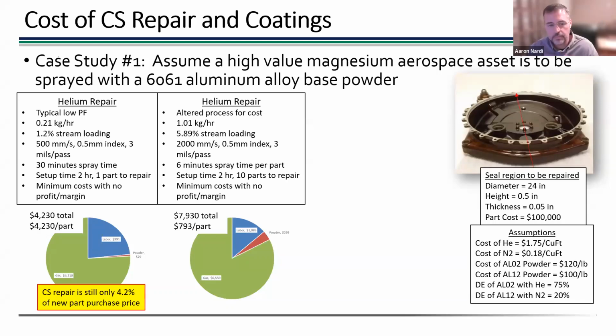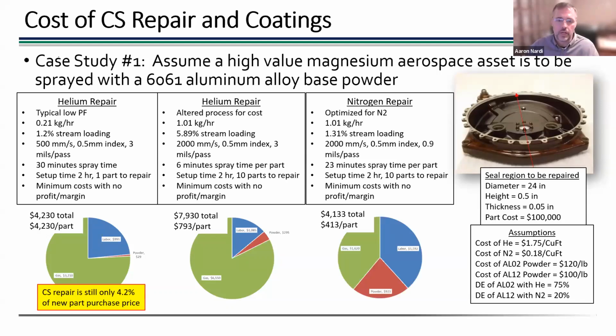significantly lower cost. Now you can go a step further and go to nitrogen, but now your increment is much smaller, right? You're going from $800 to $400. It's still an improvement, and it could be very important, especially if there's difficult logistics in getting helium, right? But the difference between the first two is a much bigger factor.